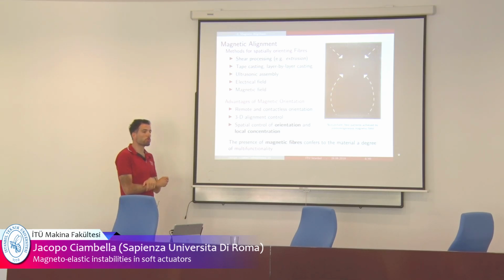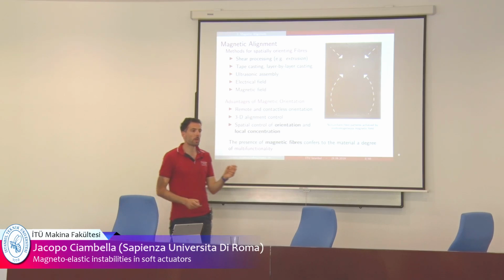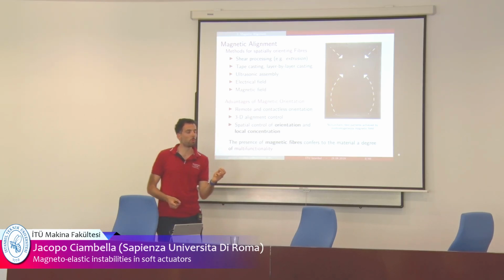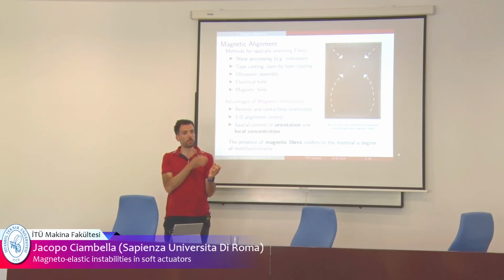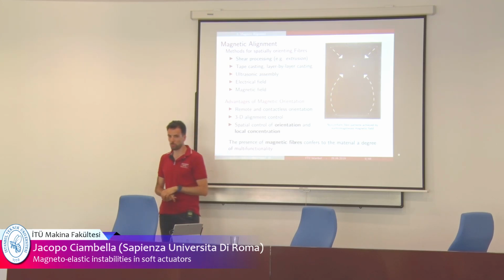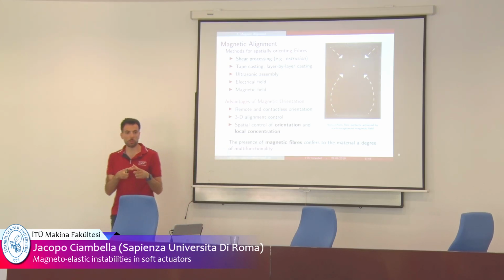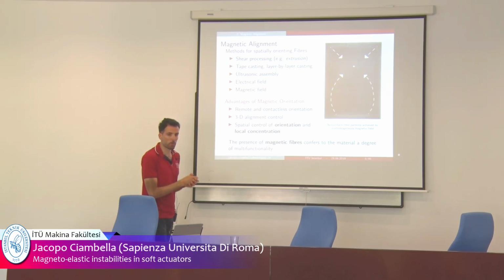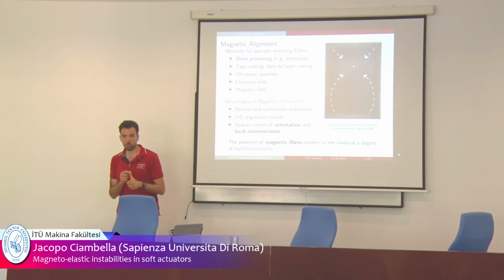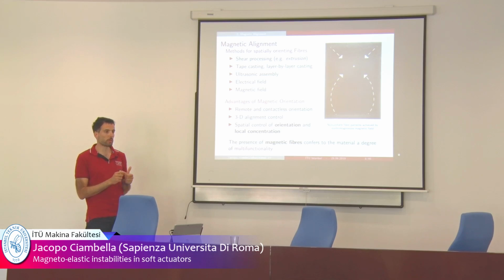You can do ultrasonic assembly. If you have a viscous solution and you send into this viscous solution an ultrasonic wave, the ultrasonic wave can be tuned to have orientation of the reinforcement inside this viscous solution. But this is normally carried out only for very small specimens. Then you can use electrical field or magnetic field. Why magnetic field? Magnetic field is contactless compared to electrical field, so you can do that remotely.